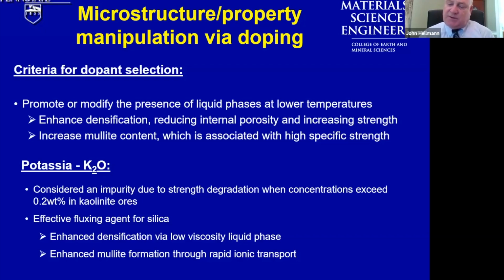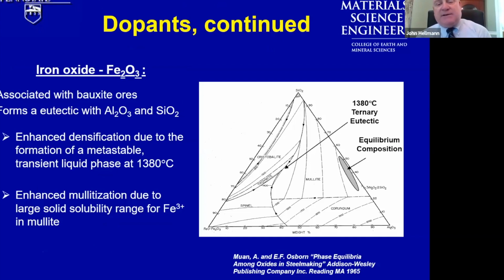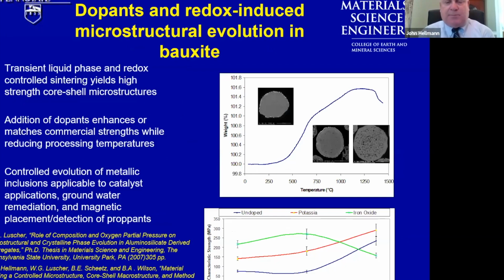So we embarked upon a series of experiments in which we dramatically expanded the level of dopant concentrations outside of the common impurity levels. We exploited transient liquid phase sintering to achieve high levels and rapid densification, at the same time achieving requisite crystalline phase assemblages to achieve high strength. And some interesting things cropped up. We were able to densify the materials at a couple hundred degrees lower than what was traditionally being used in the proppant industry to get full density and high strength, strengths commensurate with the very best commercial state-of-the-art materials.